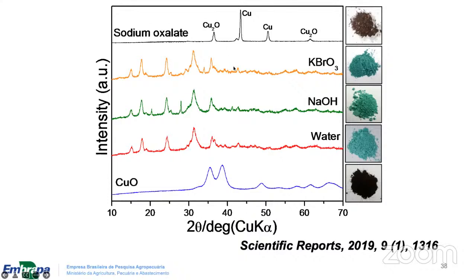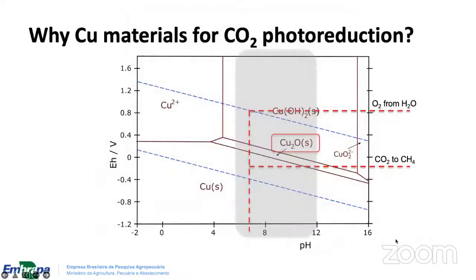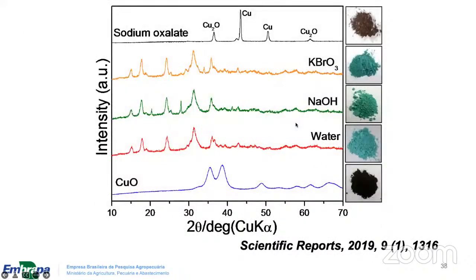This system in some way is confirming the idea that the light application with the CO2 is reducing the material, and all the reaction of CO2 reduction is taking place over metallic copper instead of copper oxide. So in the other cases, we can come back to the idea of the Pourbaix diagram. We can understand that the material has been eroded and is forming a second phase, a copper carbonate, by the contact with the CO2.